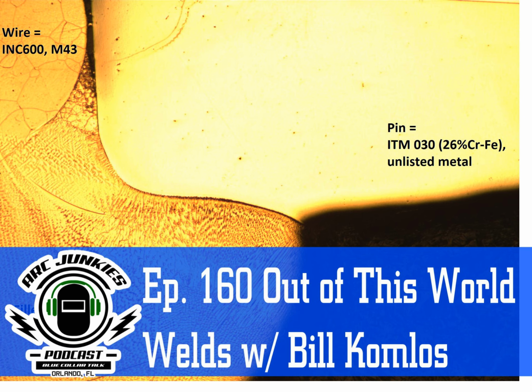And these are 2-inch thick flanges with 1.5 inch thick webs, okay? And to move these things, we'd shrink down for the closing seam. And I welded up. I have minus 300 degrees at my back, giving me arthritis. And I got 2,700 degrees, well, 10,000 degrees at the electric arc for a flux cored NR232. Well, I was using Core Shield 8 to weld these things up.